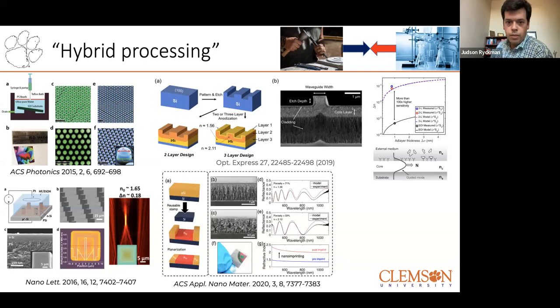So another example of hybrid processing, this is some work that we've done recently where we've shown not only can you change the refractive index electrochemically by changing the porosity, you can change the refractive index mechanically by compression. So if we take a high porosity porous silicon film, let's say it's 71% porous, maybe the film looks like this. Again, I mentioned those pores are much smaller than the wavelength, so we don't have very significant scattering. We have a relatively well-behaved effective medium, and you see that in the Fabry-Perot interference measurement, which matches the model pretty nicely. The refractive index is pretty low, it's 1.4. We could make it even lower if desired.